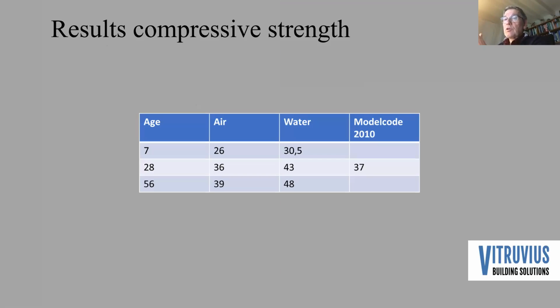And afterwards, we made a lot of test specimens, and about half was cured underwater at 20 degrees, and the other half was cured in air. And you can see what is happening. The water cured gave the nice result of about 43 megapascal at 28 days for a C30. Air cured only 36. Next, please.